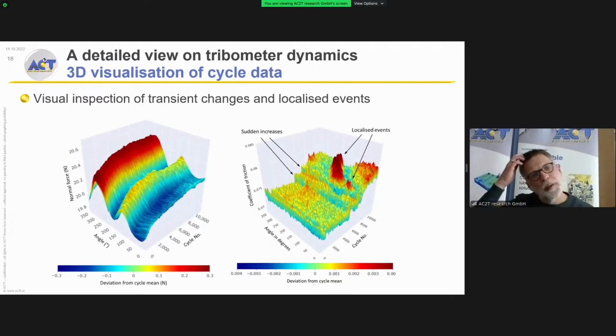Another very powerful tool which we developed in our company is what we call a 3D visualization of cycle data. On one axis you plot the in-cycle position. In our case, it's simply the rotation angle of the disk, but in a linear oscillating test rig it may be the position within one cycle. On the other axis, you plot the cycle number. Then you can clearly see, and also measure, effects which are localized, that means which happen only in a certain position of the disk, and which are transient in nature, as opposed to those which happen everywhere. To my point of view, this is very useful in any kind of tribometrical experiment to get a clear idea of what's going on, and then, of course, to pre-process your data for further analysis in a good way.